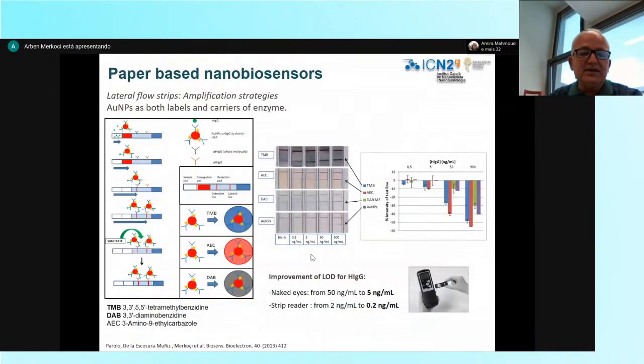For example, to make these devices more sensitive, what we did is we connected the gold nanoparticles with some enzymes. In this case, we immobilized some HRP enzyme, and then instead of detecting the gold nanoparticles, we detected some byproducts of these enzymes using some substrates, for example, TMB, DAB, AEC, which are usually used in immunochemistry, so well known for some applications in this area. So by using these modified gold nanoparticles, we are able to see a much more sensitive signal.